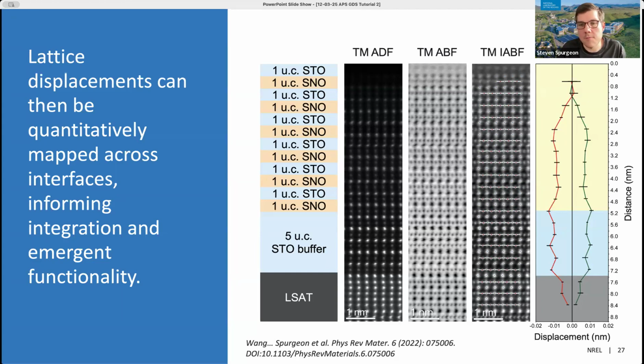This is another example of where we're analyzing superlattices. What we're looking at here is, again, breaking down the material into its sublattice components, devising measurements of all the atomic positions, and then measuring these displacements in a quantitative way. Ultimately, what we get out of this very basic statistical analysis is something that goes way beyond what we would do manually. It's much more reproducible and helps us to better understand ferroelectric behavior.